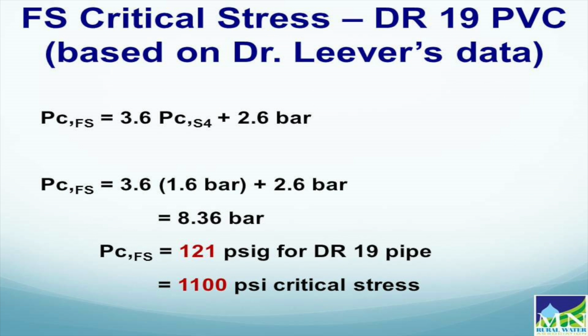Now, if we take that exact same equation and plug in 1.6 bar for this DR19 PVC pipe, we get a critical pressure of 121 psig, or a critical stress of 1100 psi.